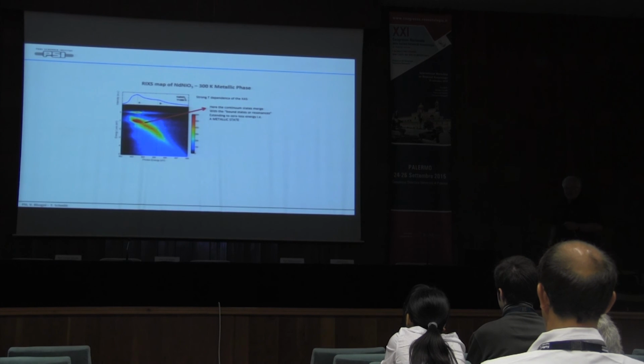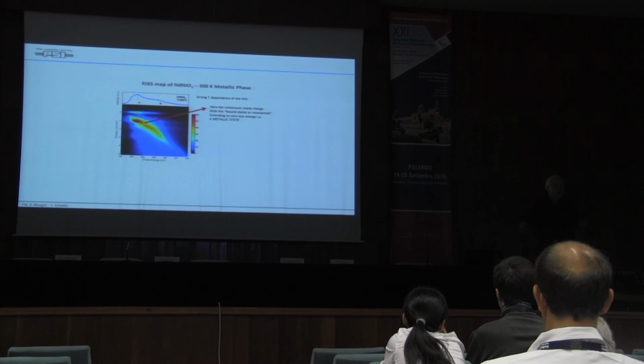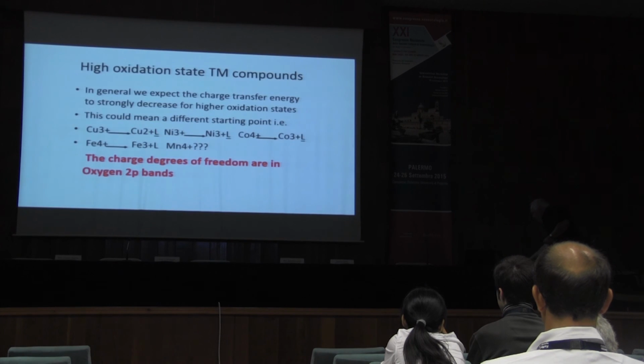Now you go to the metallic phase, and that gap closes, and those continuum states extend all the way down to zero energy. Now that's hard to see because you know that your oscillator strength goes to zero when you're down there anyway for charge excitation. Okay? So, but still, this really goes all the way down. So these lowest energy states, these metallic states, are states which involve oxygen 2p holes, actually. Now, how does that work?